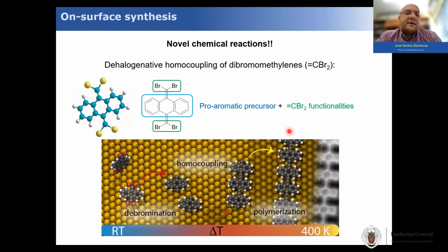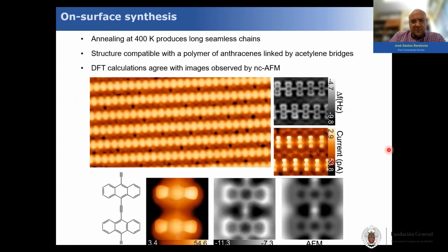By the same time this article appeared, we were already obtaining similar results, but with a more sophisticated system like this one. Here we also have the dibromomethylene groups, but they were linked to a pro-aromatic precursor, in this case an anthracene backbone. When we anneal the deposited molecules on the surface at 400 Kelvin, we see very, very long seamless chains, and the structure is compatible with the formation of acetylene links between the different anthracenes, as you can see here, forming long polymers. This was confirmed by the DFT, as I already said.